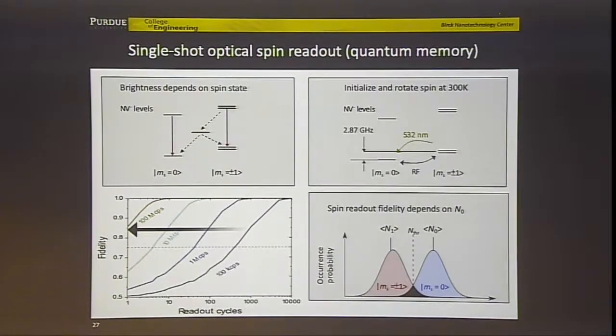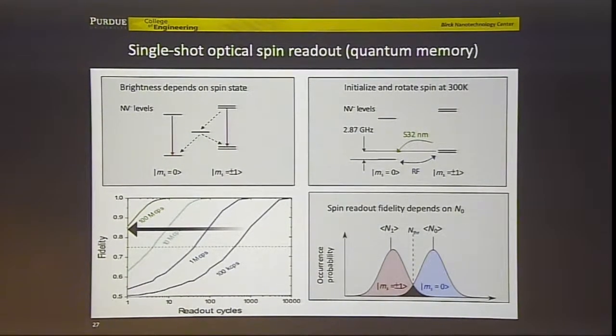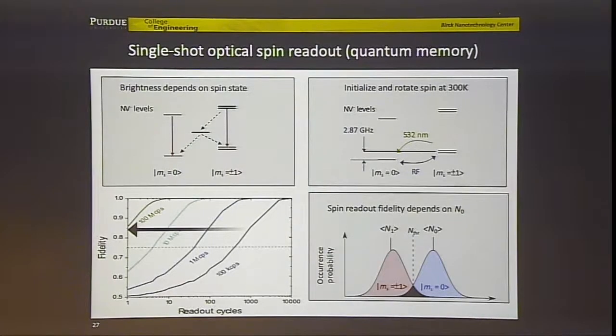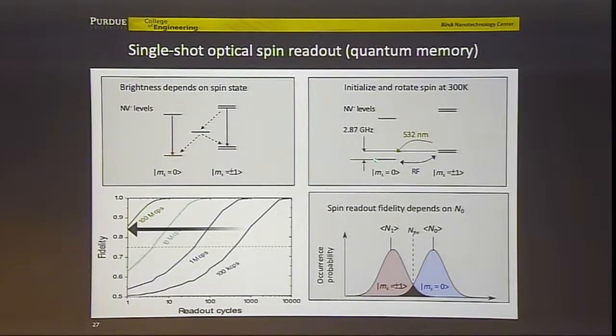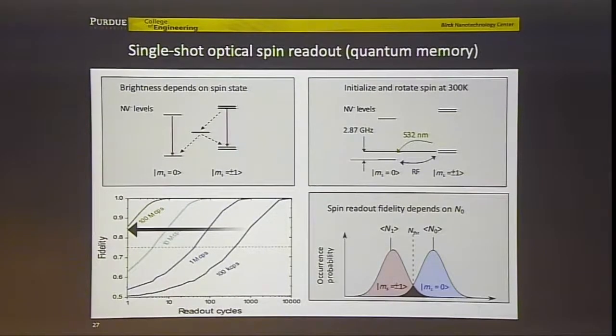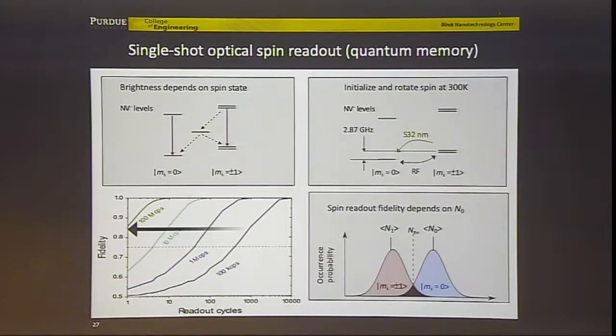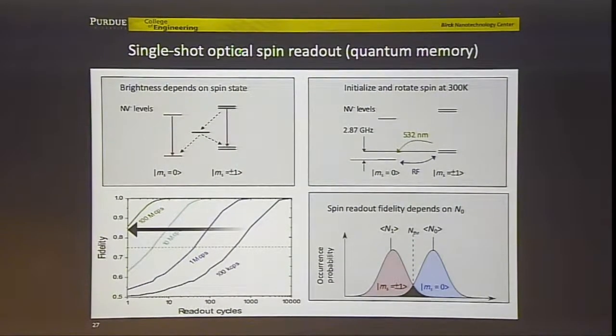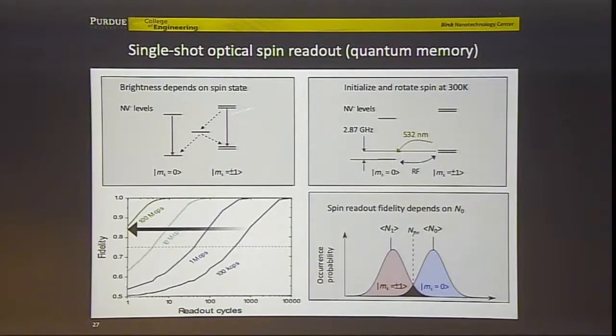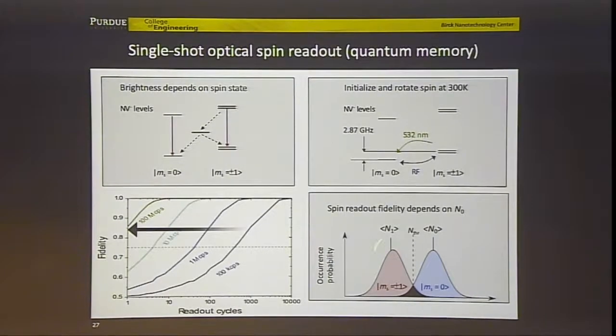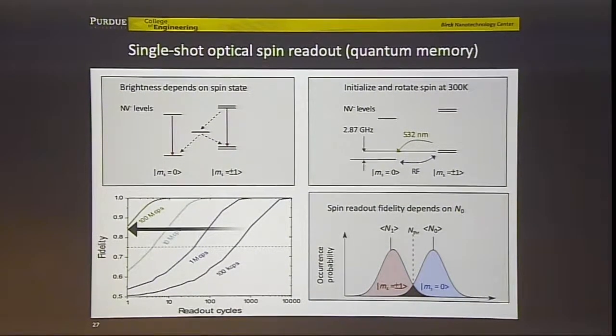Yet another thing: I mentioned this spin degree of freedom in nitrogen vacancy could be used as quantum memory, which you could write and control by microwave radiation. You could, for example, switch spin from 0 to 1 by applying microwave radiation. That would be like a bit flip from 1 to 0. And I could read it optically. The trick, though, when I read it optically, is that fluorescence for the S equals 0 system and the S equals 1 system is different because of this non-radiative channel. By looking at fluorescence, which occurs at slightly different frequencies, I could say whether it's spin 0 or 1.